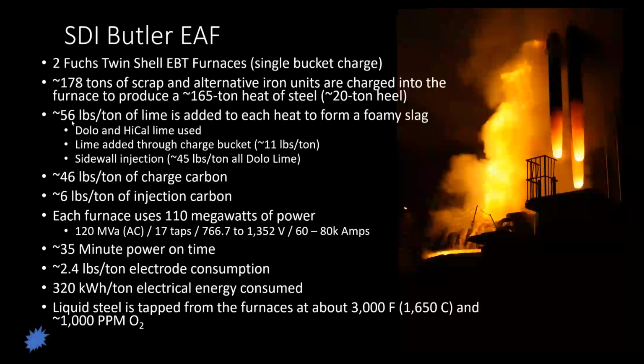We end up using about 56 pounds of lime per heat, and the bulk of that is through sidewall injection. We're using about 45 pounds per ton of dolo. Our lime - we're looking at about 11 pounds added to the charge buckets, 11 pounds per ton. We're using about 46 pounds per ton of charge carbon, larger pieces of carbon going into the charge buckets, plus about 6 pounds per ton of injection carbon.